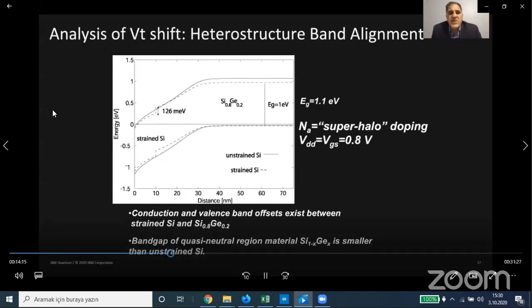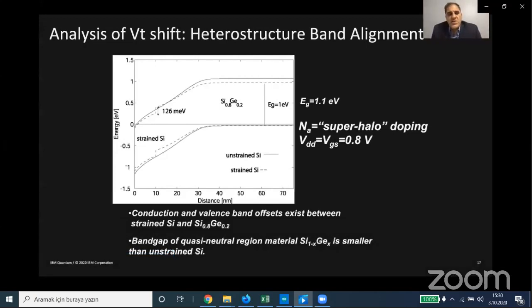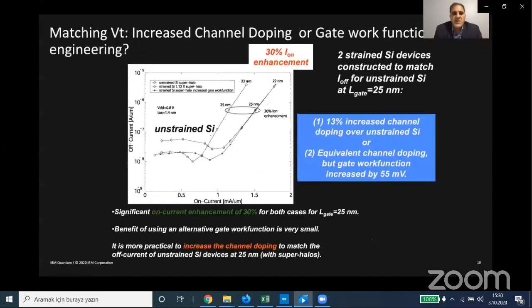Hence, to achieve the same VT, you have to either increase the doping of the strained silicon, which adds to the issue of the Coulombic scattering described earlier, or one can use a different work function for the strained silicon to offset this VT. What's shown here is a simulation showing unstrained silicon, Ion versus Ioff, versus a strained silicon device that has 13% higher doping than the unstrained, and then a strained silicon device that just increases the gate work function. As can be shown here, down to 25 nanometer gate length, significant boost in performance is seen, 30% specifically.